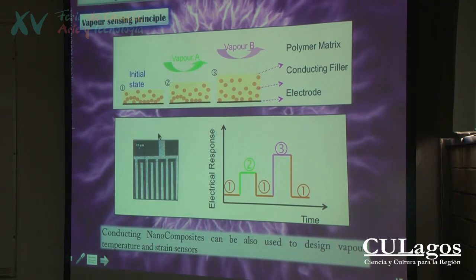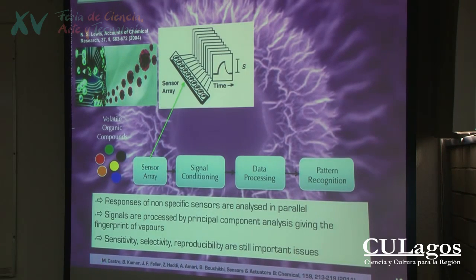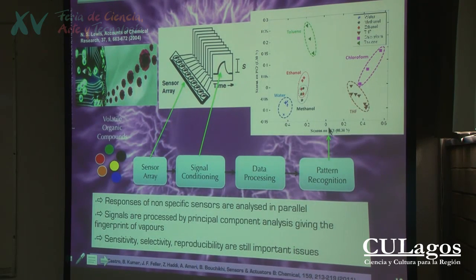So it's possible to use such kind of nanocomposite to make sensors, so sensitive materials, sensors that can detect gas molecules. So you need to put the sensor on an electrode, and then the interactions between the organic molecules and the sensor will trigger an electrical signal that you can analyze. If you combine different sensors like this, you can make an electronic nose which will allow you to separate different vapors that can be present in the atmosphere, vapors of solvent like chloroform, ethanol. In the field of composite, you can analyze styrene, which is released during the synthesis of the composite, for example.